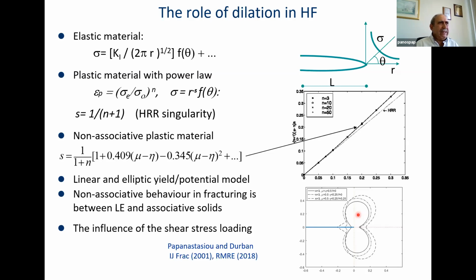And we tried with some analytic work to look also at the influence of the dilation, of non-associativity. And we found that the non-associative solution is between the elastic solution and the solution we get for associative solids. So the non-associative is in between. One of the things we found with non-associativity is that it gives a kind of boundary layer in the stress concentration near the fracture tip.